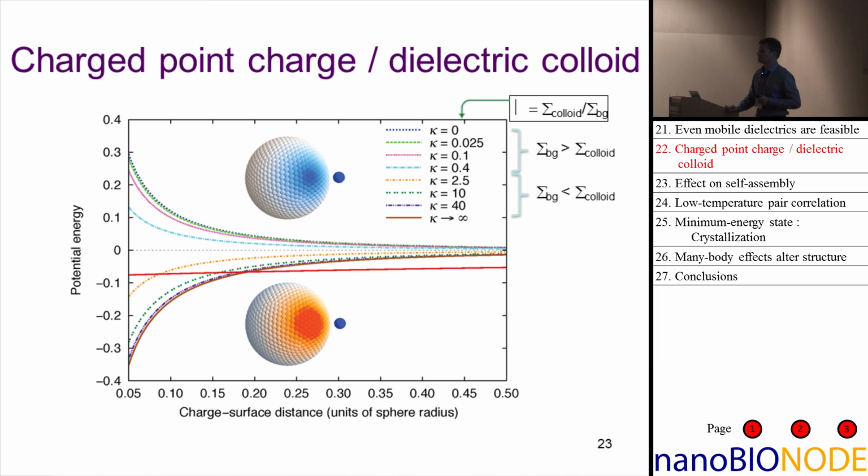But take the same material and put it in a very low dielectric constant solvent, an organic solvent, acetone, anything like that. Take the same negative charge. It actually will induce its own attraction. It will induce a positive charge on the part of the colloidal surface closest to the negative charge. So there's a lack of symmetry here. And we can see how that actually affects self-assembly.